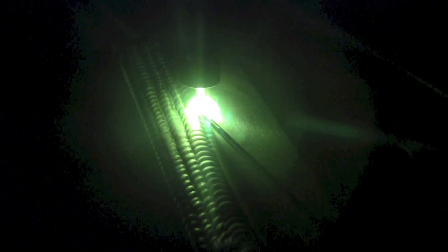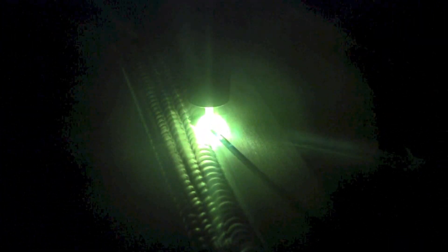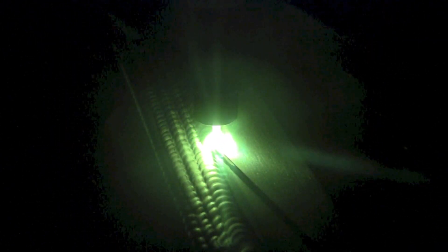Now we've turned it up and we're operating at 175 hertz. Real smooth, clean arc. You also need to make sure that we maintain the proper arc length. You want to keep no more than one-eighth of an inch. Closer the better. But you also don't want to get down there so close that we touch the tungsten to the filler metal. Nice rhythmic, even ripples moving right down the plate. There's the first five passes.